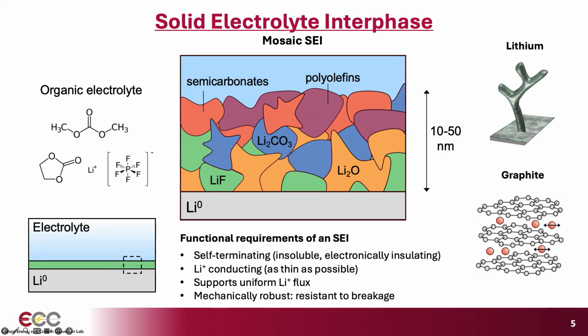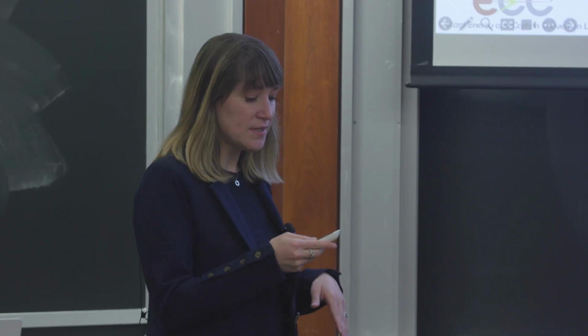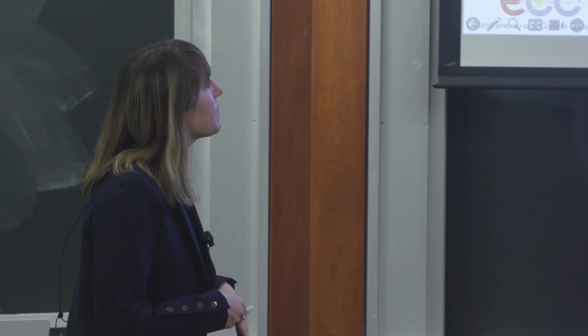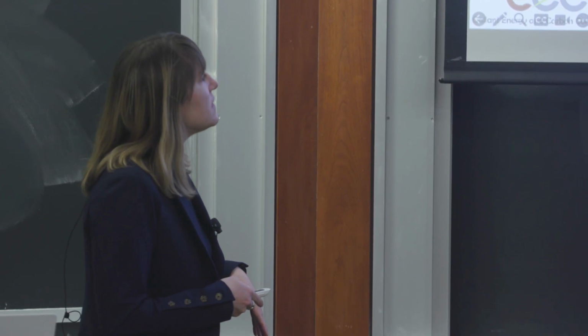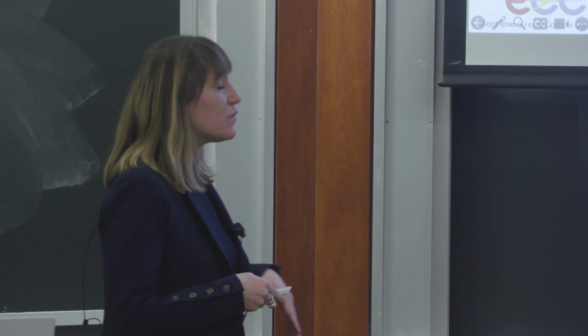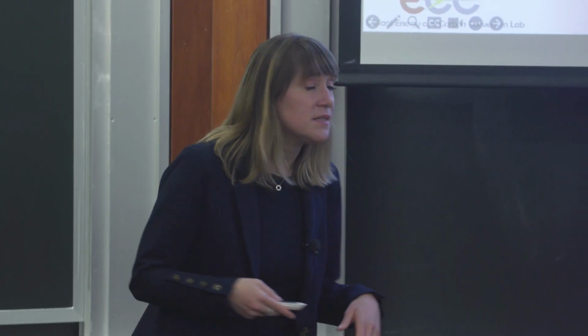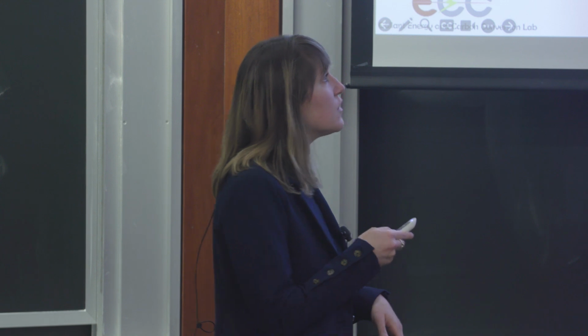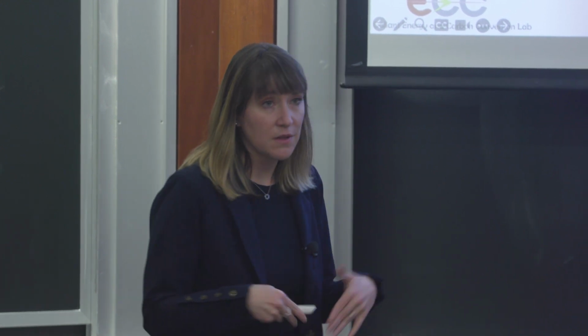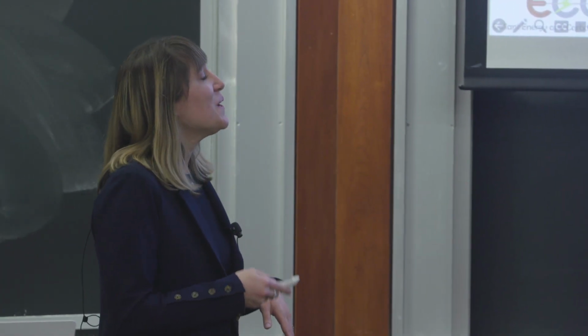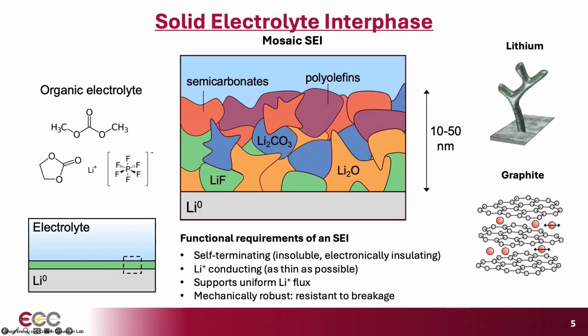Very fortuitously, the SEI is lithium ion conductive. So you can transport lithium through it, you can plate it underneath, and then you can reverse that process in a stripping process. Other functional requirements of the SEI, we want it to support uniform lithium flux as much as possible, and it needs to be mechanically robust to accommodate the volume changes that occur during lithium metal plating and stripping. And I want to emphasize that graphite also faces similar challenges in a way.